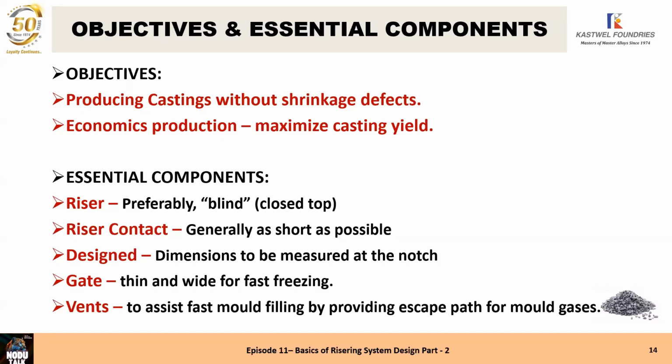Gate. The ingates in the SGI casting, when you are doing riser design, have to be thin and wide for fast freezing. We want to isolate the running system from the casting and the riser after pouring is over, so the only connection is the gates. So we want to freeze the gates immediately after the pouring is over, so that the casting and the riser are separated, to see how the riser feeds the casting and produces a shrinkage-free, defectless casting.